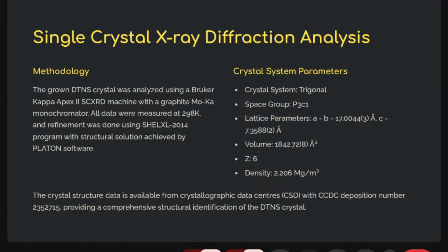So single crystal XRD we have tested in IIT Madras at room temperature, that is 298 Kelvin, and we have used SHELXL 2014 and PLATON software to get the single crystal analysis. From the single crystal analysis, we got the crystal system is trigonal. The space group is P3c1, and the lattice parameter is a equal to b equal to 17.0044 Angstrom, and c is 7.358 Angstrom. And this crystal structure is available in the CSD file with the CCDC deposition number 2352715.